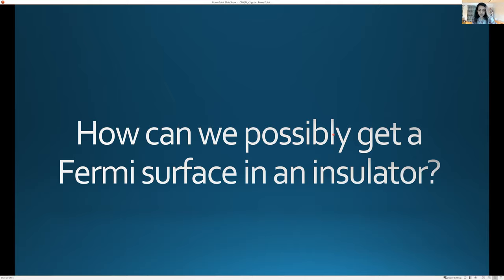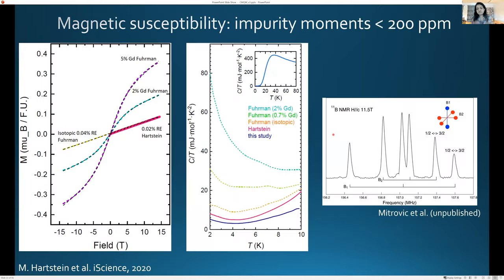Firstly, one of the possibilities suggested is, what if it comes from a metallic inclusion? So we look at the most likely possibility, which has been looked at by the group of Tyrrel McQueen and Collin Broholm at Johns Hopkins. They deliberately doped the sample with a percentage of gadolinium. If it's doped with gadolinium, one now picks up this magnetic behavior in the magnetization. So one would see a bigger magnetization and this curvature just from a Langevin fit. What we find in our crystals is a very, very small component.